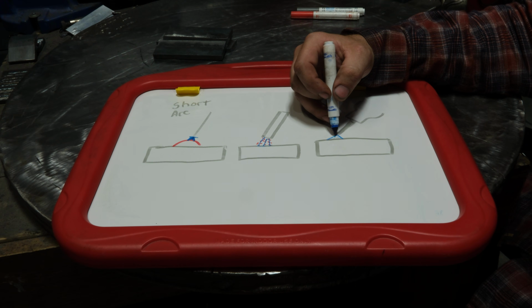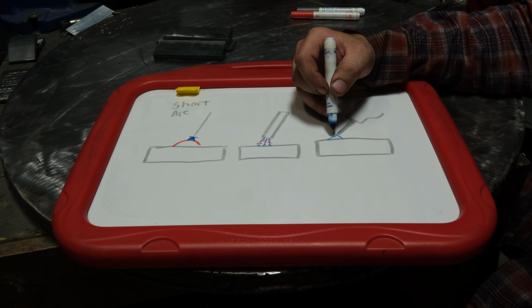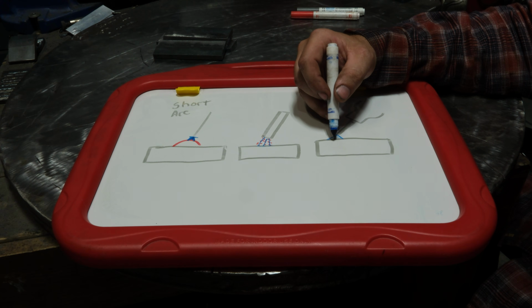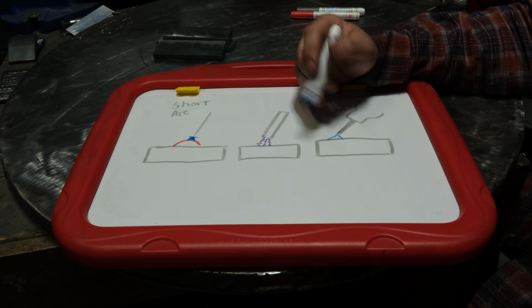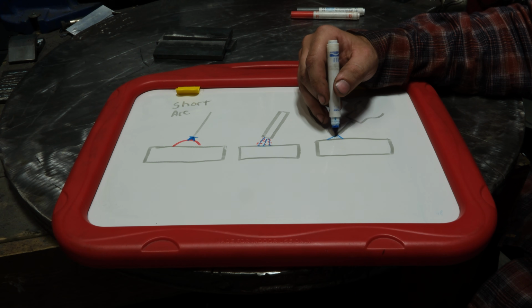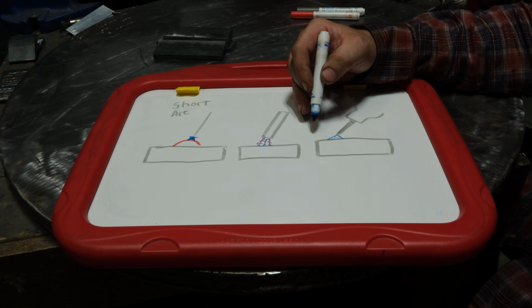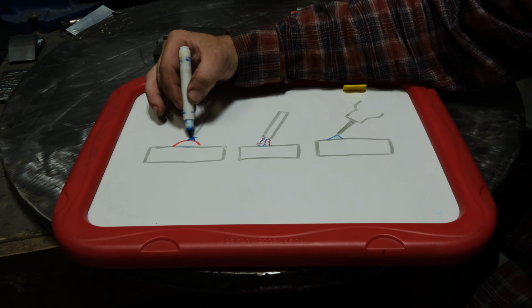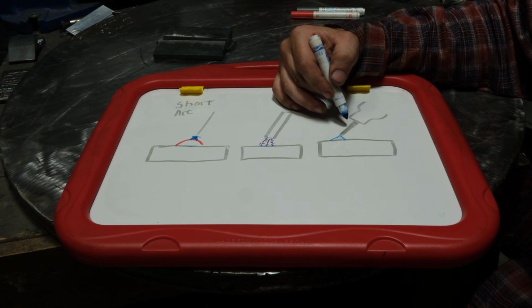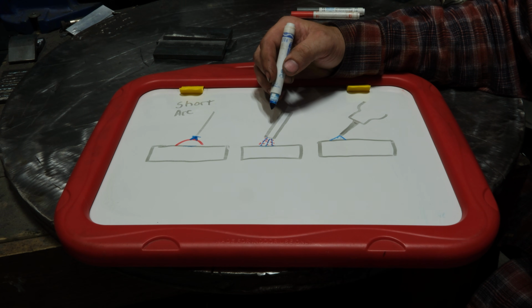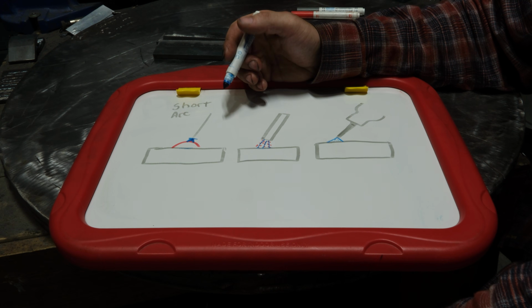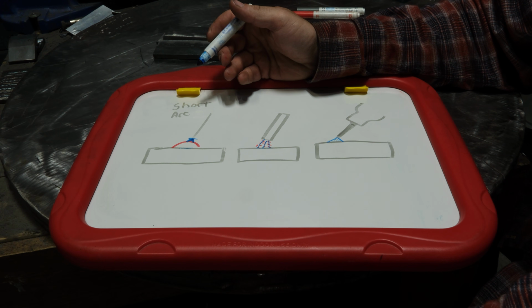Now with TIG, you have basically a tungsten and an arc, and then you add filler wire manually. Therefore, your arc is always on that base material, and the only time you tend to have lack of fusion with TIG is running too low an amperage and doing something like lay wiring or pushing too much filler, where the puddle goes cold and then it doesn't fuse into a root. But because you have basically an arc on its own, you can achieve 100% root fusion without issue, because, well, you're welding directly there. All of the heat is right here instead of right here. And that is why the stick process and the TIG process arguably have no limitation on the thickness of material they can weld. You're probably wondering, well, with the MIG process, I just multiple pass everything and it's fine.